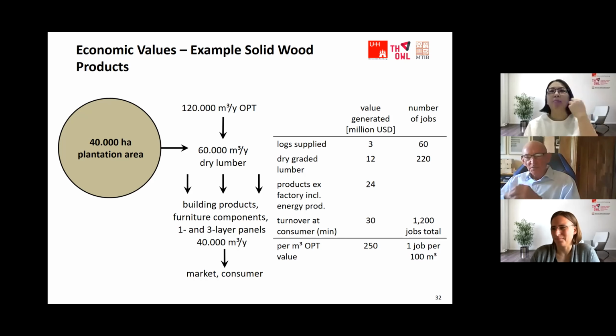So just one remark here, an example for the economic values. If we take a 40,000 hectare plantation area, we get continuously about 120,000 cubic meters of oil palm trunk from this area. The transportation distance is very short. This is a very big advantage for oil palms. And from the 120,000, we get about 60,000 cubic meters of dry lumber.